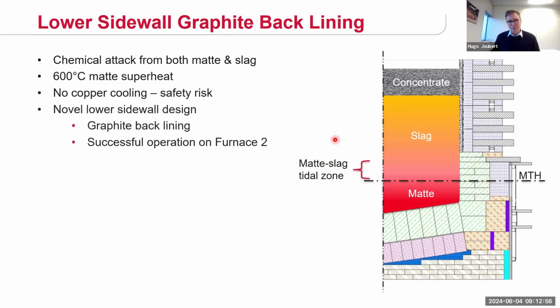So the design that we implemented is what we developed also for furnace number 2 at Sibanye, and it's been working there now for 12 years very well. It consists of your working lining and then a back lining that's basically graphite against the furnace shell with forced air cooling on the outside. And the idea is to extract all the excess heat from your working lining in this critical area.